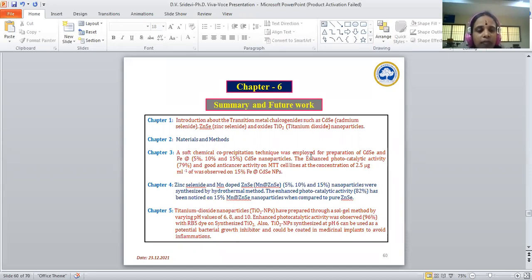In chapter 5, TiO2 nanoparticles have been prepared through the sol-gel method by varying temperature and by varying pH values such as 6, 8, and 10. Enhanced photocatalytic activity of 96% was observed with an anionic dye, RB5 dye, on synthesized TiO2 nanoparticles. Also, TiO2 nanoparticles synthesized at pH 6 can be used as a potential bacterial growth inhibitor and could be coated on medical implants to avoid inflammations.